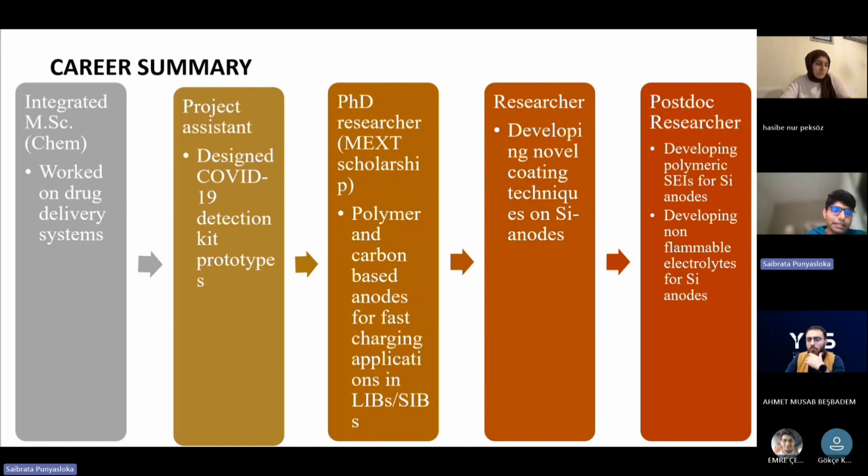Even though they are fine and the performance is good, we are not achieving a total solution. After a fire starts, there is a time at which the fire completely extinguishes, and that takes longer. If we have a completely non-flammable electrolyte, there is zero chance of a fire. But it is very difficult to develop a non-flammable electrolyte because the performance is very bad. There are different reasons; that is probably another story for another day where we can talk just about non-flammable electrolytes.